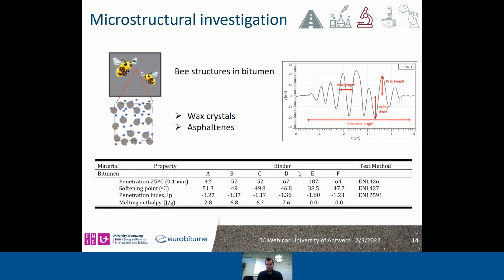It should be noted that binders E and F, which were wax-free, didn't show any features in the surface microstructure before or after aging. So the focus was only on the waxy binders, and for that reason we investigated waxy binders before and after standardized aging simulations of RTFO and PAV.